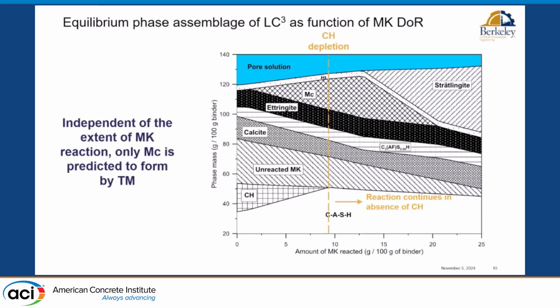What's interesting, though, is that we start seeing some disagreements between what we observe experimentally, which is always a mixture of hemi and monocarboaluminate, and what thermodynamic models tell us. So for an LC3 type of system, thermodynamically, we should only be observing monocarboaluminate, irrespective of the degree of reaction of metakaolin, right? So you can be at any point of this line, which is degree of reaction of metakaolin, and the only AFM phase that you're going to observe is monocarboaluminate.